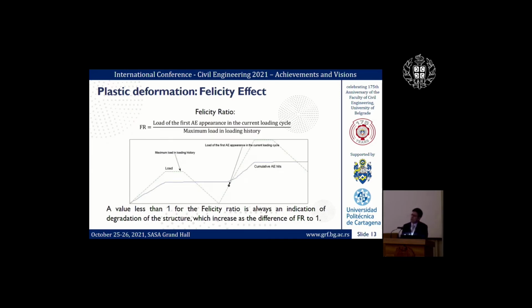This effect is used to try to quantify the damage of your structure by using what is called the Felicity ratio, which is the ratio between the load at the first appearance of emission in your current loading cycle and the maximum load in your loading history, so the maximum previous one. Obviously, any value of the Felicity ratio less than 1 is always an indication that there is degradation in your structure, which increases as the Felicity ratio gets further from 1. The lower it is, the more damage or degradation you have in your specimen.